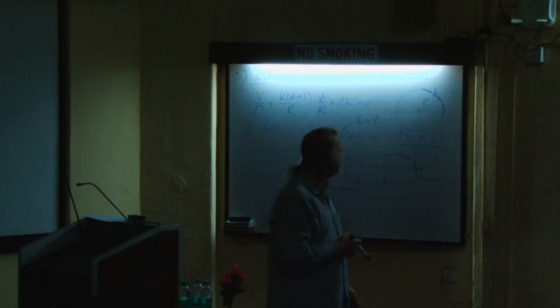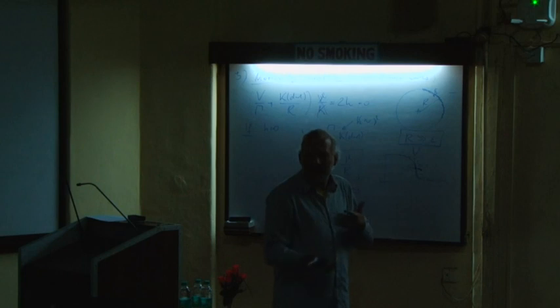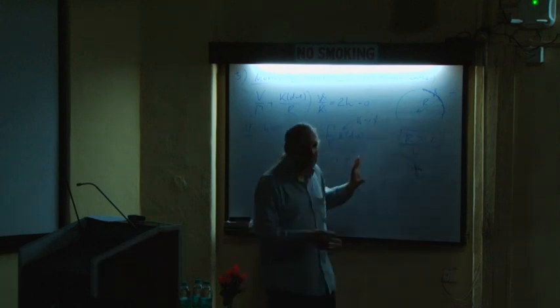And notably, this is what happens for grain boundaries, because grain boundaries are precisely in this case. If you have a grain boundary that separates two grains of the same phase, that means that the free energy of the two sides of the interface is the same. And so if the grain boundary is curved, it will move. And it will move in such a way as to reduce the grain boundary surface. So this is the physical effect that is at the origin of grain coarsening.